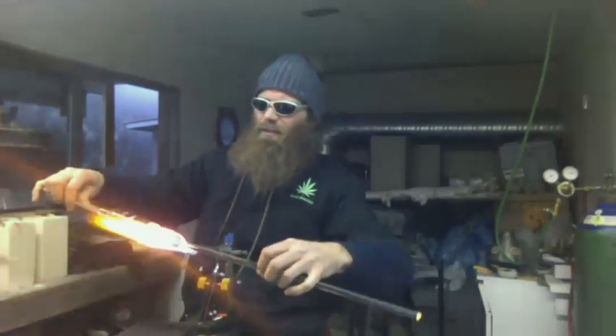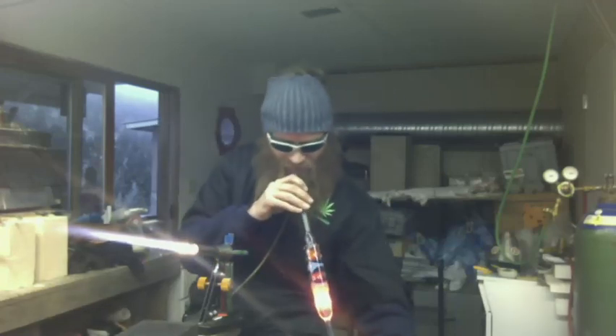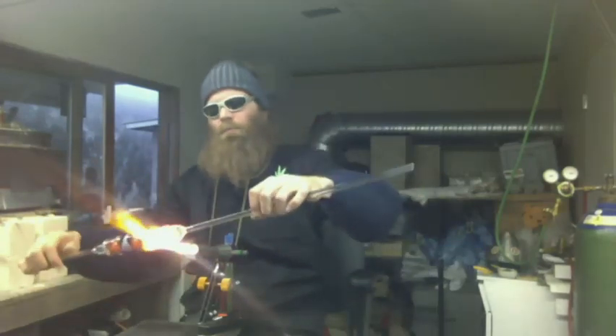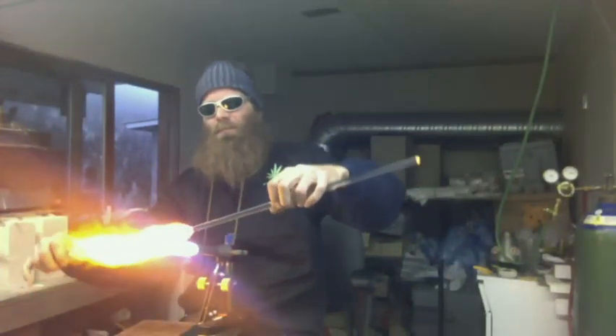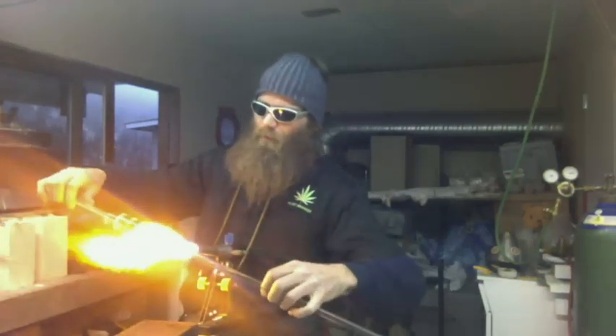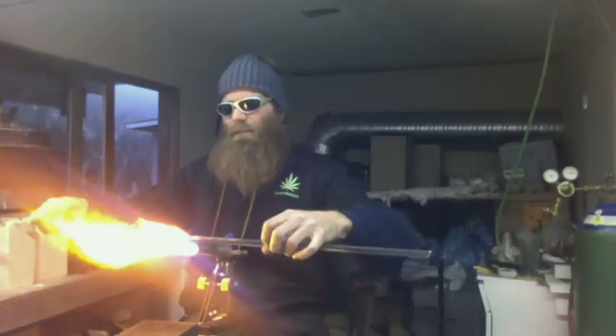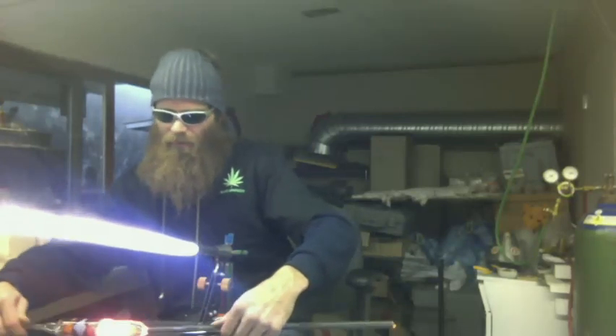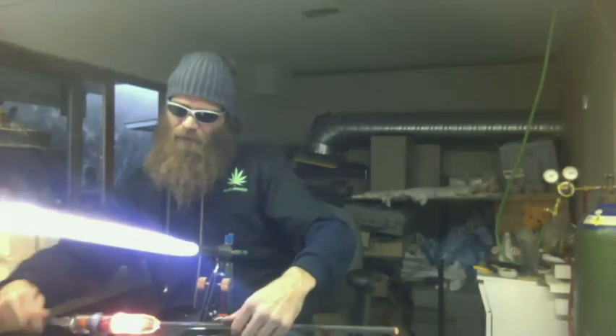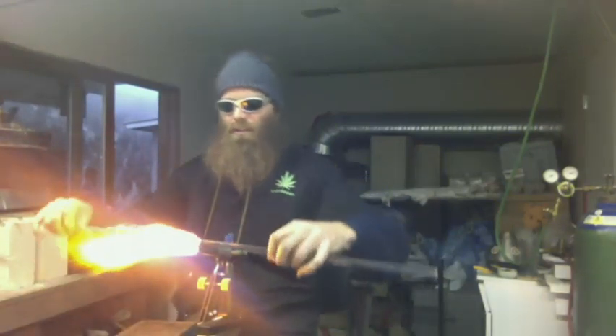I'll show it to you in a sec actually, it's on the top of the kiln. One of my first salt carving type pieces. Yeah, it worked out pretty good, but this one here cracked because of the Amazon bronze color that we used. Every color likes a different torching atmosphere is what I'm trying to say. And Amazon bronze definitely likes an oxidized atmosphere, so that needs a lot of oxygen in your flame.